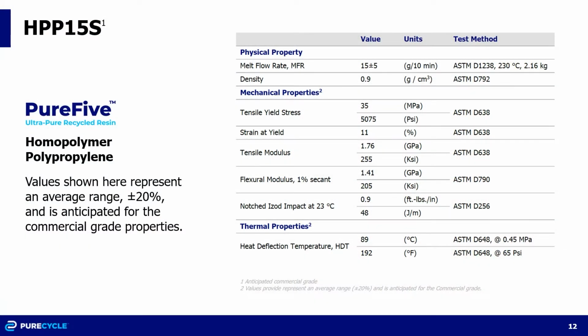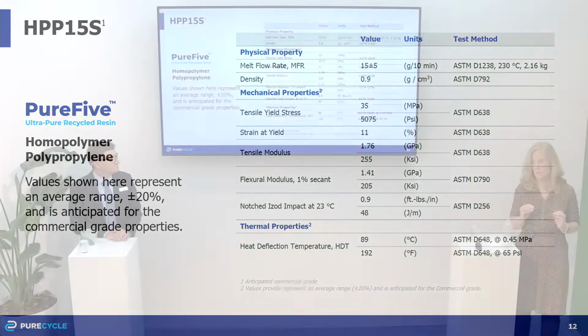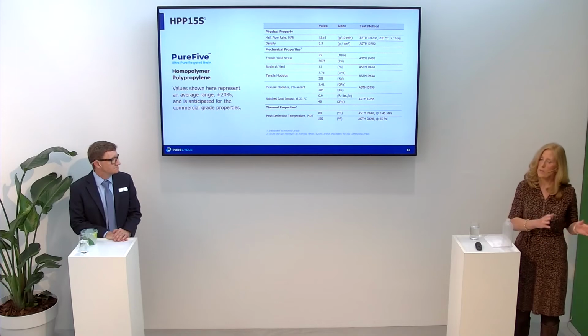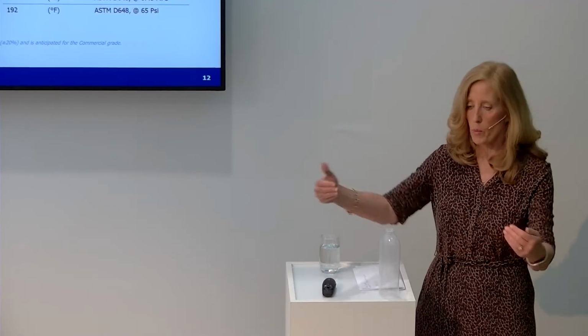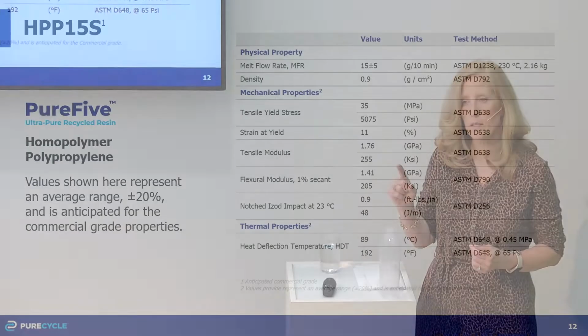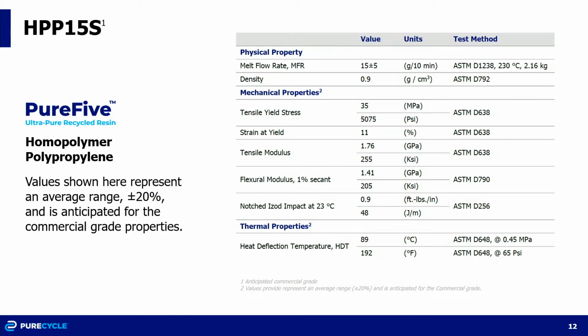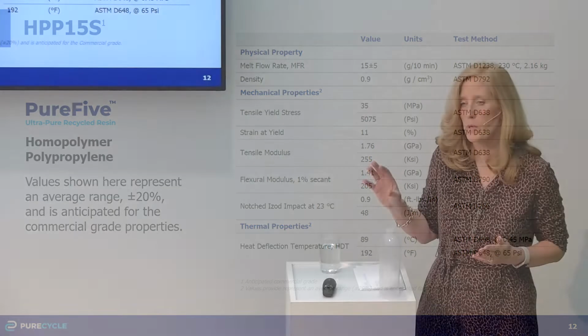So initially, when we make our resin, our goal is to blend. We're blending, and we've been doing this for a little over a year now in our pilot plant where we consistently make a 15 melt. When I see enough critical mass of a lower melt flow, or I see enough critical mass of a higher melt flow within the streams that I'm feeding and blending to run on a line consistently so that I'm not going up and down and changing out and cleaning out, then I will have those melt flows. And as I mentioned, our goals and our targets are to do 1 billion pounds.